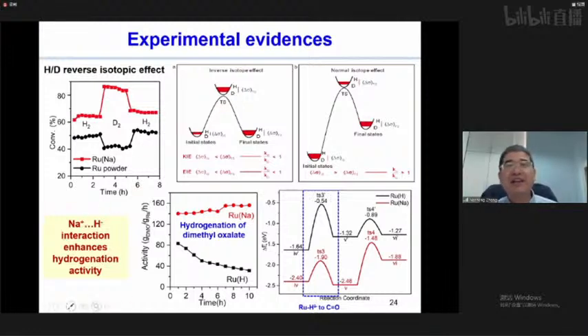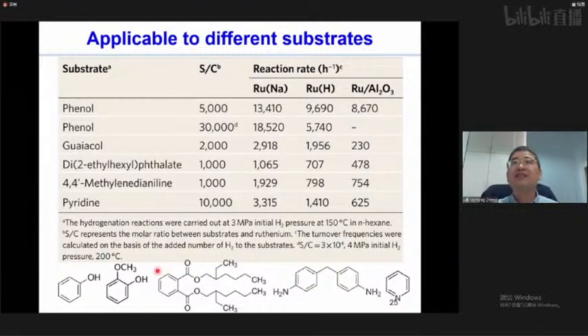And simultaneously, this electrostatic interaction can also enhance hydrogenation activity just because it reduces the hydrogenation energy barriers. So that's why this catalyst is highly active for the hydrogenation of benzene rings as well as pyridine rings. So it's really powerful and stable.